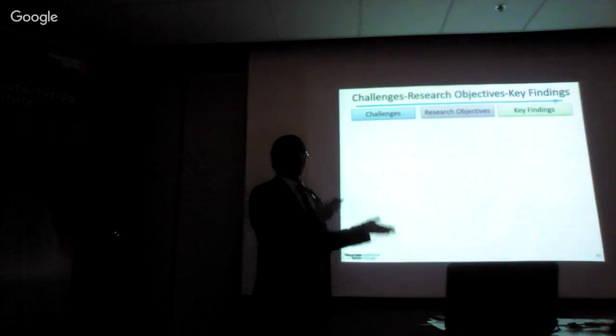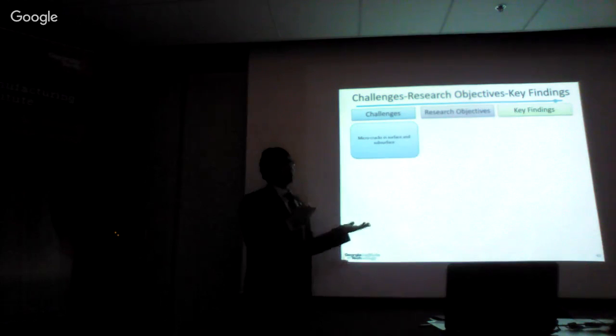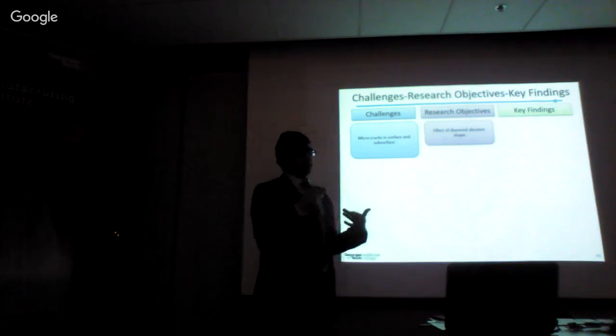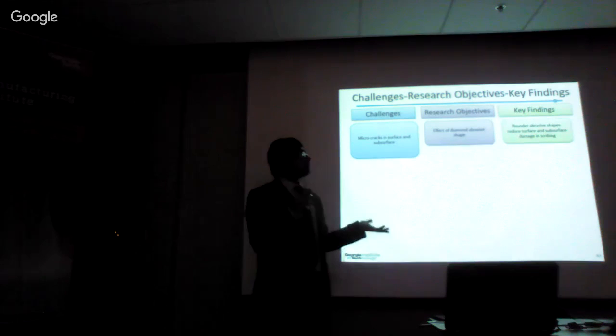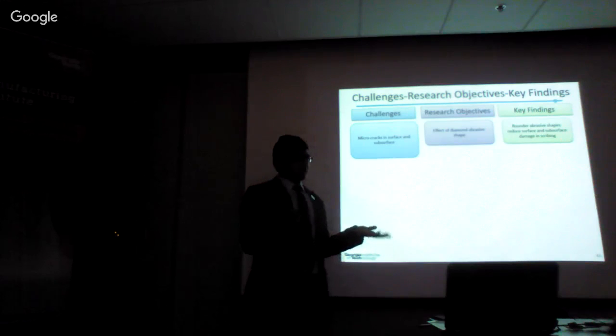Moving on, to wrap up, I'll revisit what the challenges are, look at the research objectives which were motivated by the challenges, and talk about the key findings which have addressed those challenges. So the first challenge we mentioned was the micro cracks in surface and subsurface. And one of the ways of addressing that was the effect of the actual diamond abrasive shapes. We found that the rounder abrasive grit shapes reduce surface and subsurface cracks during the wire scribing experiments.